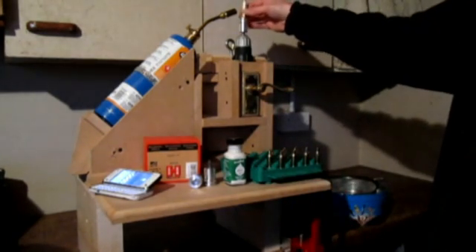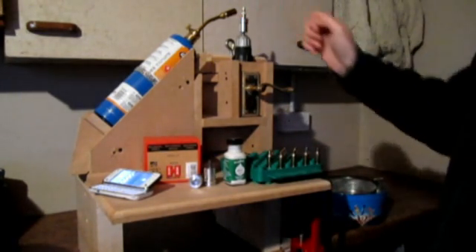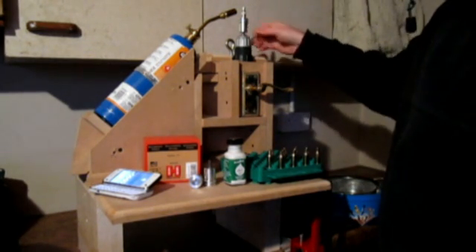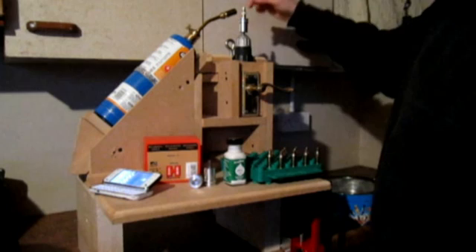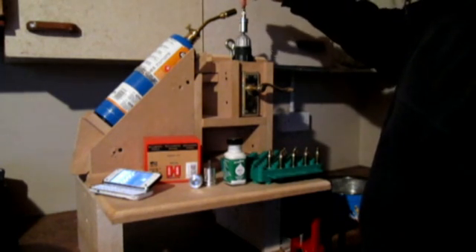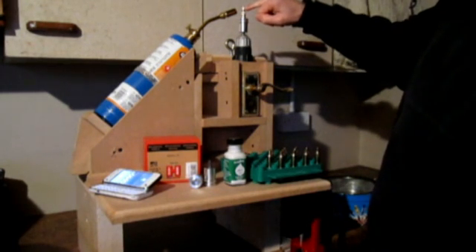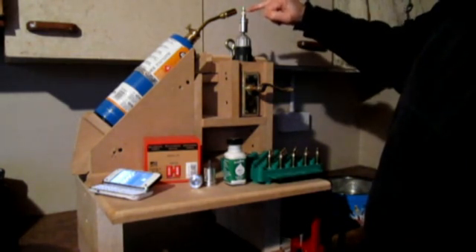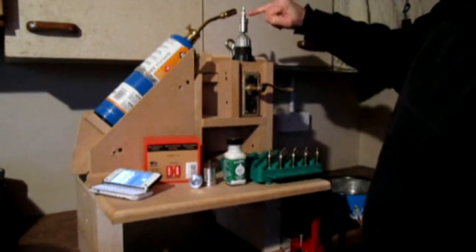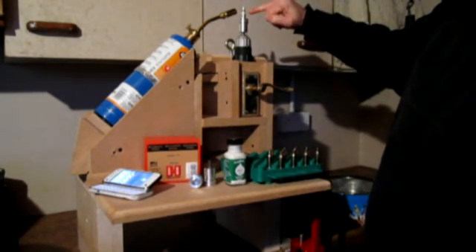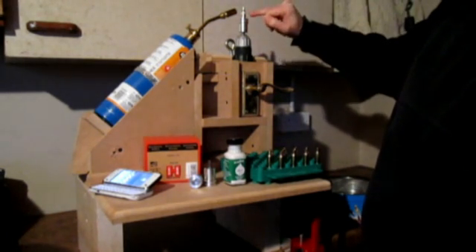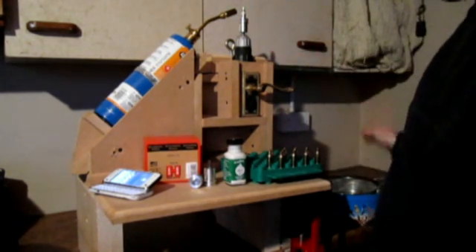I'll replace the case into the holder. I'm going to begin to rotate the drill head so that we have it turning because I want to get continuous and uniform heat of the whole case neck. The flame should center onto the middle of the case neck. The heat will travel down through to the case, melting this indicating liquid, turning it almost invisible. It may leave some residue which can be cleaned off after. Once that completes, I remove the case from the holder and into the pan.